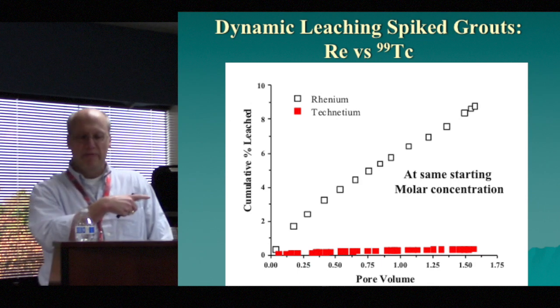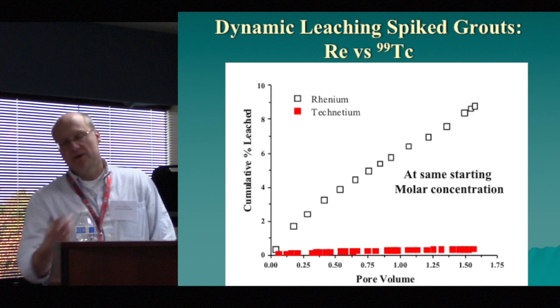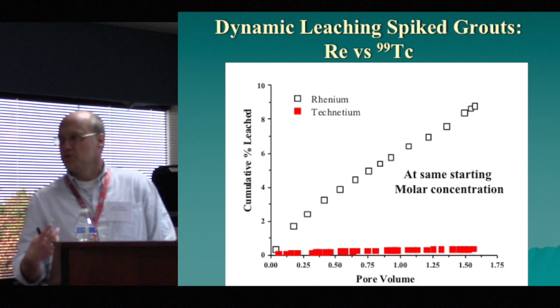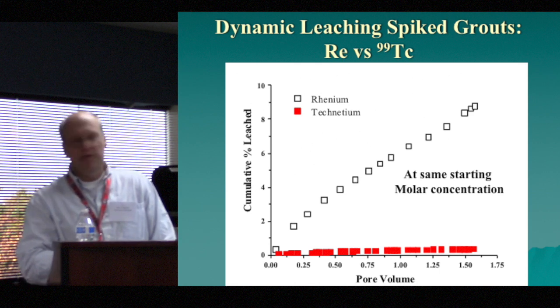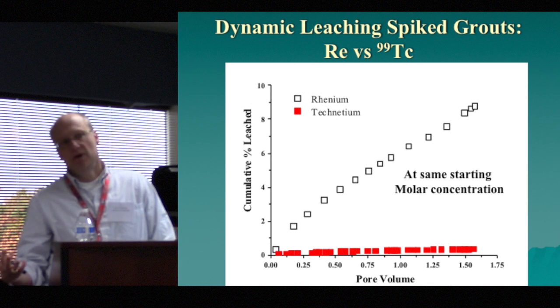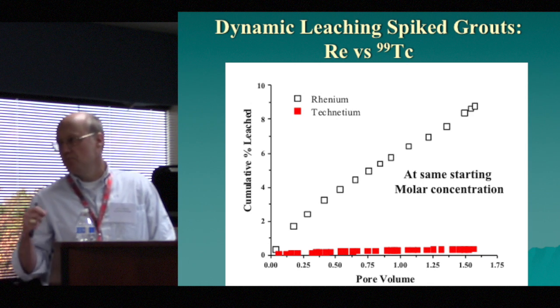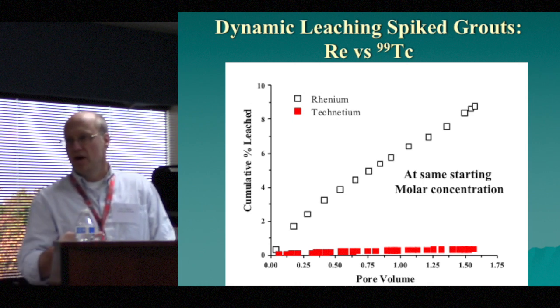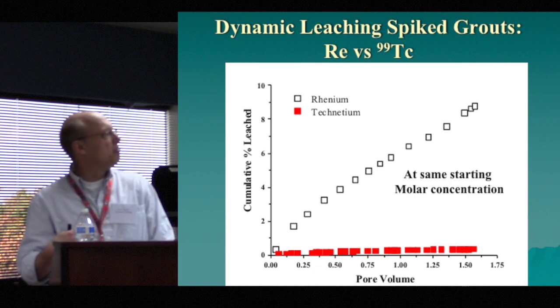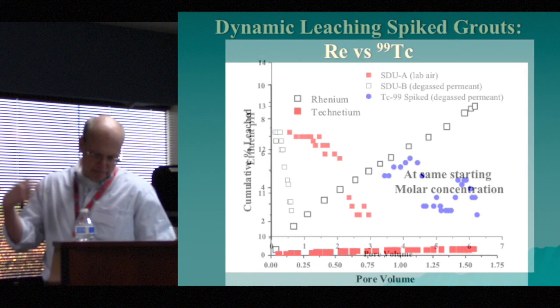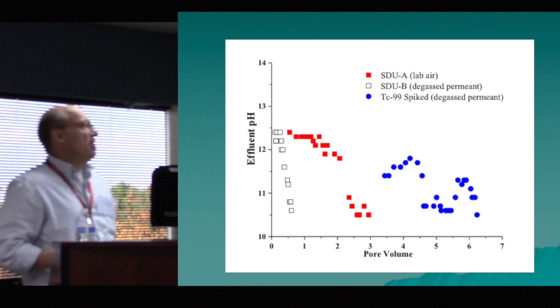The one thing that we've tested early on is that we can actually do a tritium tracer experiment through this material and get a better idea of what the actual conductive volume is, because it's likely much, much less than what the porosity measurements tell you it might be. Next slide. So here's some of that data.